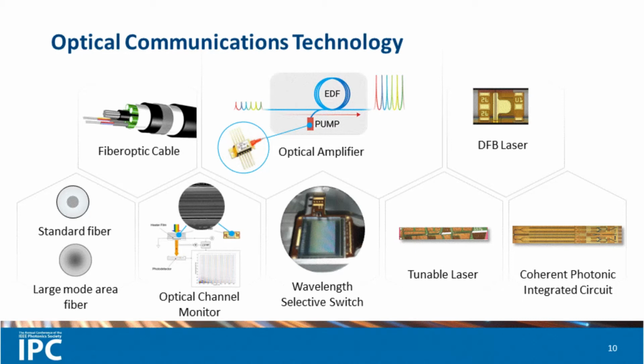Now, once multiple wavelengths were on a fiber, additional inventions were required. Large effective core diameter fibers with carefully engineered dispersion profiles were necessary to mitigate the deleterious nonlinear effects of optical interactions such as four-wave mixing between the channels and the fused silica core. There also became the need to monitor the powers of the individual wavelengths.